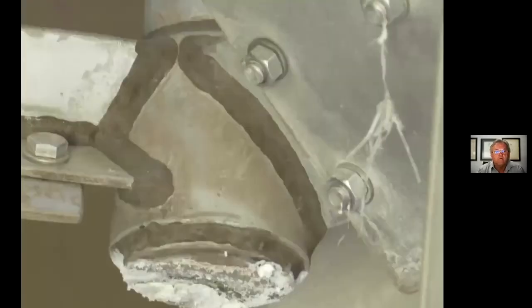Here's a photograph of a material that was selected based on chemistry and temperature. And as you can see, although there's some slight discoloration of the weld compared to the rest of the material, it has performed pretty well. But what wasn't taken into consideration in this particular case was erosion. And the net result was significant erosion corrosion on the tips of the impeller due to the abrasive nature of the slurry that was being agitated.